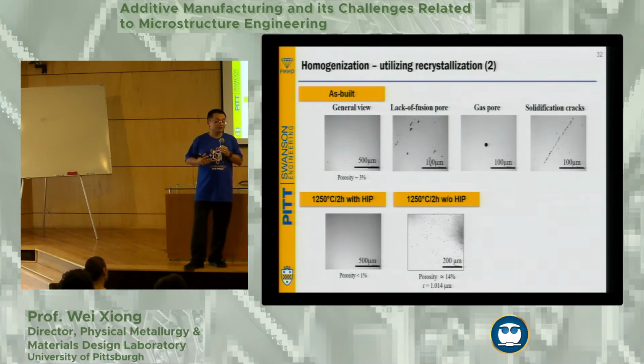So what we do is usually we just narrow it down. For example, one typical approach is the energy density - people have one parameter that is a function of all of these processing parameters, which guides us to link this localized energy density versus porosity. So you can actually pin down several of the parameters, which is generally accepted, for example for steel, and you change some - maybe hatch spacing changes a little bit, maybe layer thickness changes a little bit - but based on these two changes, you can further optimize.